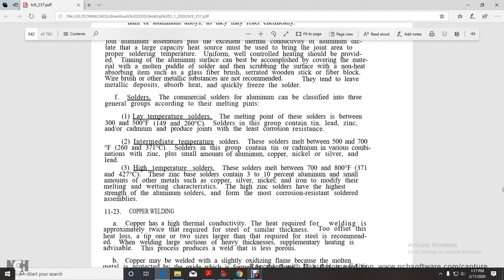All right, intermediate temperature solders, between 500 and 700 degrees Fahrenheit. Solders in this group contain tin, cadmium, various combinations of zinc plus small amounts of aluminum, copper, nickel, silver, and lead. High temperature solders, between 700 and 800 degrees Fahrenheit. The zinc-based solders contain 3 to 10% aluminum, with small amounts of other materials such as copper, silver, nickel, and iron to modify their melting and wetting characteristics. The high zinc solders have the highest strength of aluminum solders and produce the most corrosion-resistant soldered assemblies.